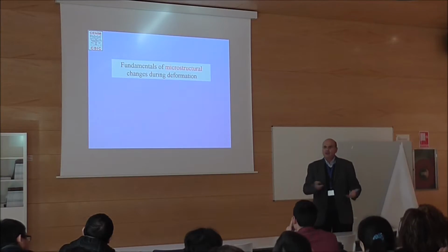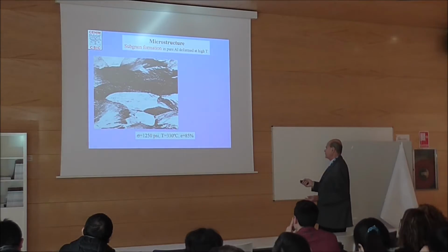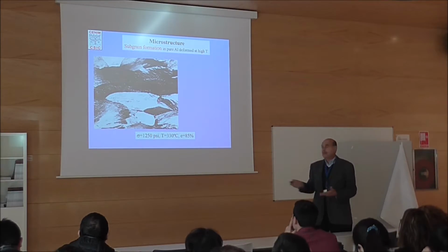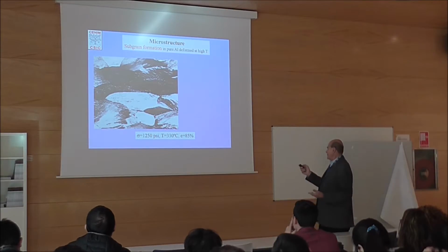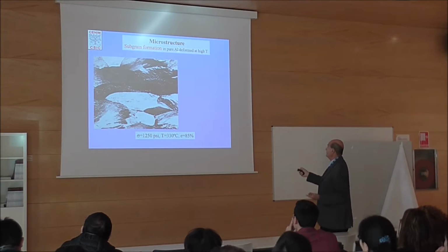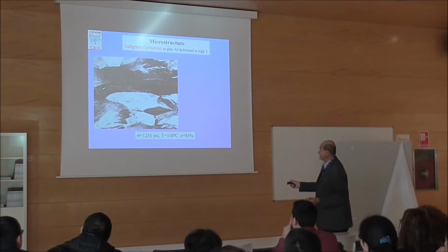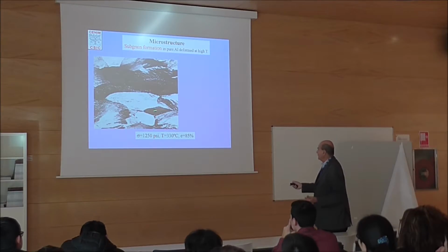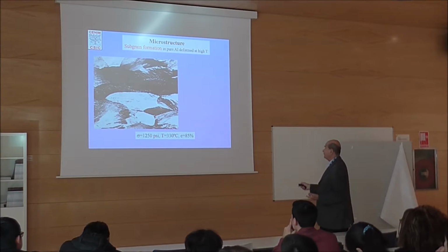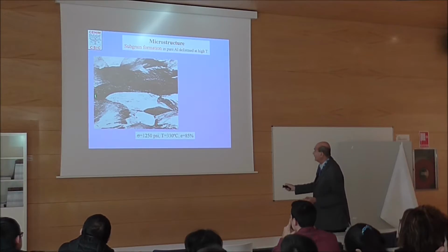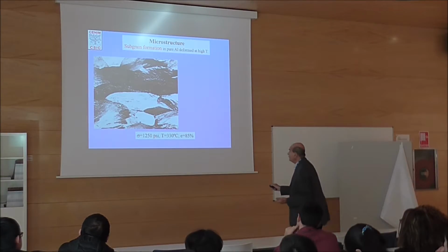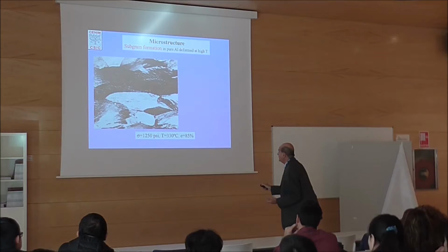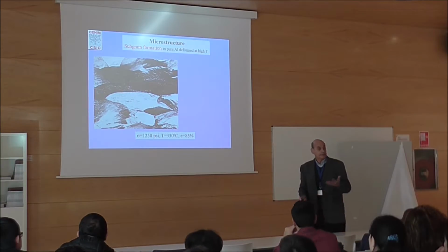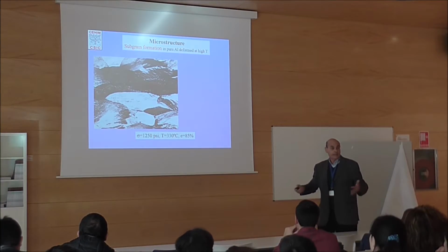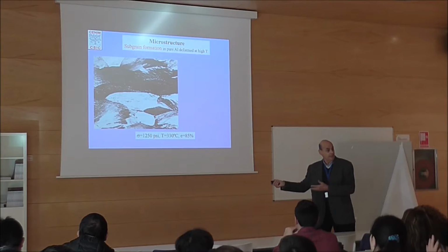Microstructural changes. What is going on when we have slip creep, and all these things? What is happening with the microstructure? The basic idea is subgrain formation. We have subgrains forming during deformation. You see, this is how the grains are very elongated because it's 85% of deformation, so we have elongated grains. And what you see here, these small things, are the subgrains. So this is the typical elongated grains and subgrains formed in the material.